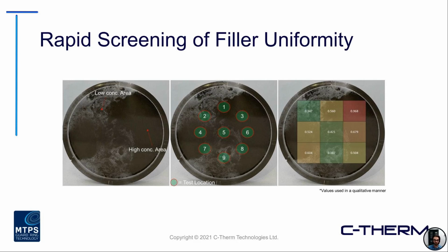But to help illustrate the point for examples where the sample that you're working with isn't visibly detectable, maybe it's an opaque material where you can't see the filler, the way to detect this can be done again with the MTPS by doing these rapid screening measurements at different surface locations. What we were able to show, if you can see those measurement locations labeled 1 to 9, is that areas with much higher filler concentrations, such as location 3, resulted in one of the highest effective measurements. Whereas at location 2, we can see much less of that filler in that area, and it had a much lower value.